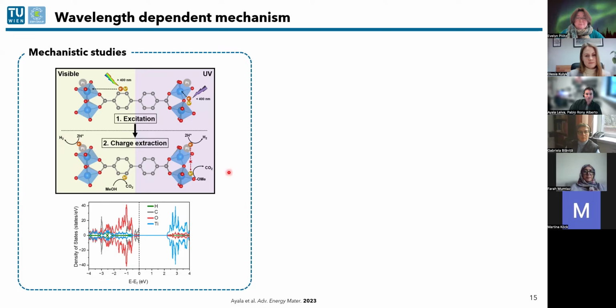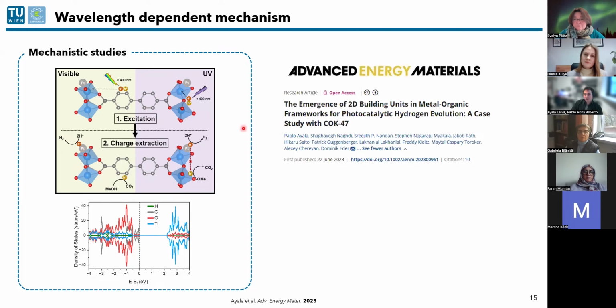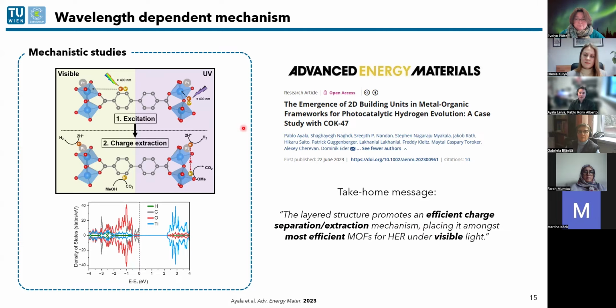And in the case of UV illumination, we were exciting states that were deeper in the valence band. So they were coming from the SBU itself. So we did not have that charge separation. And hence we were more prone to recombination, which was probably what made the material be a bit more damaged when we were using also the UV light. And so these results were summarized then in this contribution already some time back. And just as a take-home message, I would say that this layer structure is very special, and it promotes an efficient charge separation and extraction mechanism. And this is the reason why this material is so efficient under visible light irradiation.